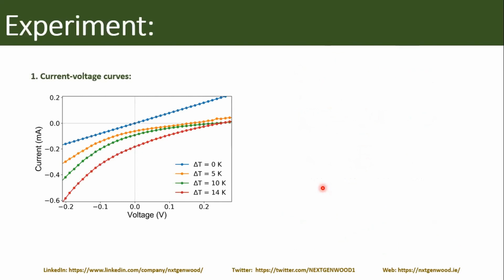The first attempt to confirm that we have enhancement of the thermoelectric effect was made using measurements of current-voltage curves, and it is shown here. First, this is a current-voltage curve of a cell with a membrane infiltrated with sodium chloride electrolyte. If we measure the IV curve at thermal equilibrium, so delta T is 0, we have a nice linear curve, which comes through the zero point.